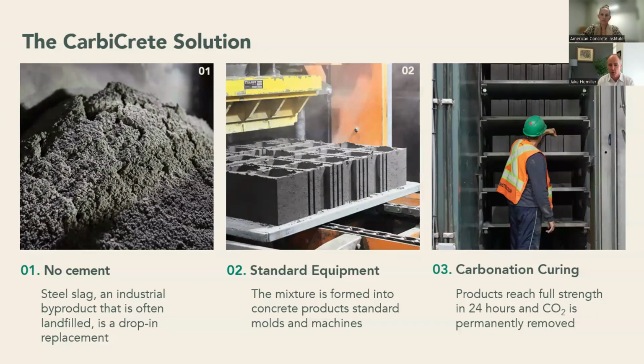Once the materials are loaded into the chamber, we shut the door, we fill the chamber with CO2, and then the CO2 mineralizes or chemically reacts with the materials that are in the steel slag to create the binder. And in that same kind of 24-hour curing time, the products come out 100% cured, so they've reached the full strength and hardness, and they're ready to go to a job site. So there's opportunities for working capital savings, but also space savings in the yard on a typical concrete products manufacturing site.